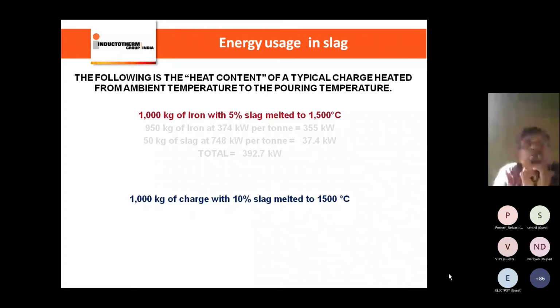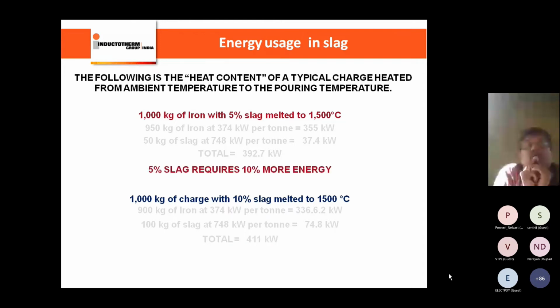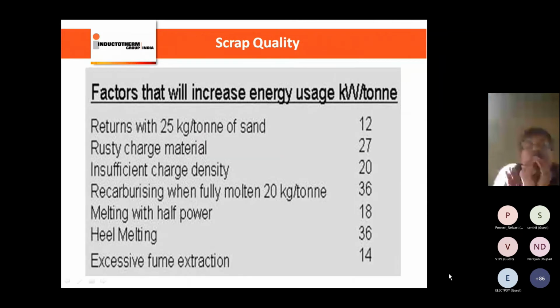Similarly, let's take 10% slag melted at 1500 degrees for 1000 kg, where about 100 kg of slag is generated. For 900 kg, the power consumption is about 336.62, and 100 kg of slag consumes about 74.8. This implies about 411 kilowatt. So what it demonstrates is that 5% slag requires about 10% more energy, and 10% slag requires 20% more energy. So these are the factors that will increase the energy usage.